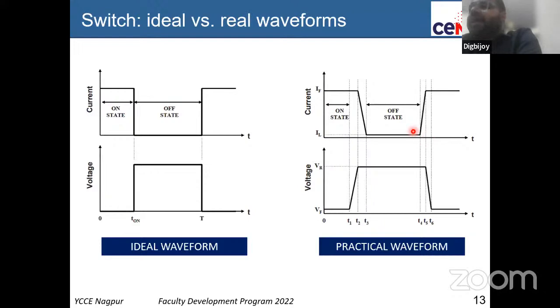That is because there is a background concentration in the semiconductor, intrinsic carrier concentration, that one cannot get rid of, that one cannot eliminate. As you go to lower temperature, you can reduce it, but our normal devices have to work at room temperature, not lower temperature. So there will be a baseline leakage current, there will be a baseline voltage drop that we cannot avoid. The objective of better and better semiconductors like gallium nitride is to make sure that the leakage becomes lower and the on-state voltage drop becomes lower. So you want negligible unnecessary voltage drop when you're switching it on, and you want negligible unnecessary leakage current when you're switching it off. These are the two important conditions.